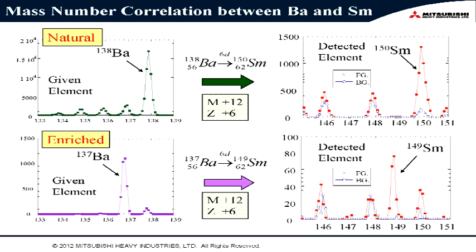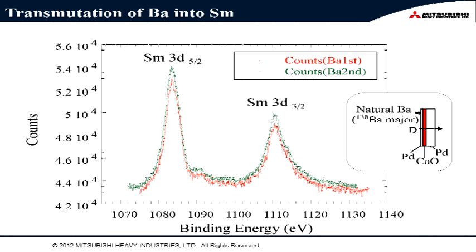We performed two types of experiments. One is a natural barium transmutation experiment, and the other is an enriched barium experiment. Natural barium has an isotopic distribution like this, where 138 is the major isotope. If we put natural barium on the surface, we get samarium, as I showed in the previous slides. And we analyze the mass distribution.